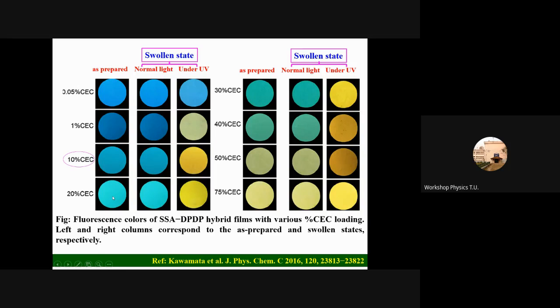Interestingly, in the first column you can see the color. This is with the naked eye, taken using a simple camera, maybe a mobile camera. You can see the images. This is blue, for all concentrations in the first column, without any treatment. Then after that, we put some solvent on the film, maybe a drop of water, or maybe DMSO, or maybe chloroform. Then again we observe, and under normal light with the naked eye, we didn't see any change. This is shown in the second column.